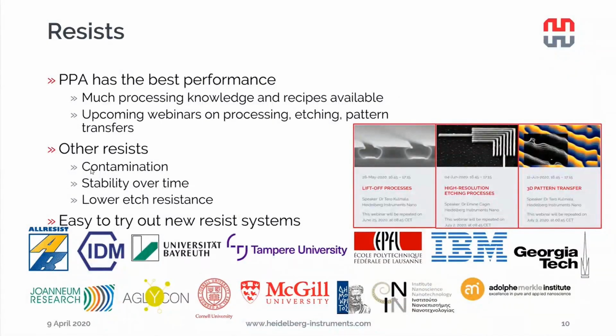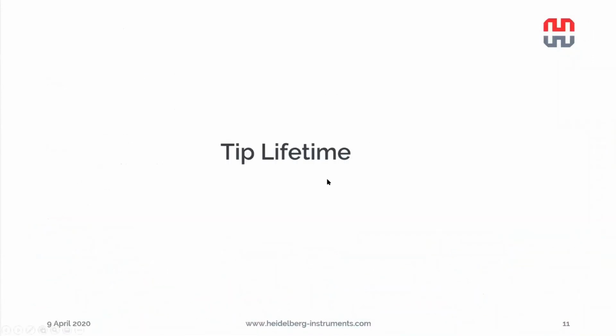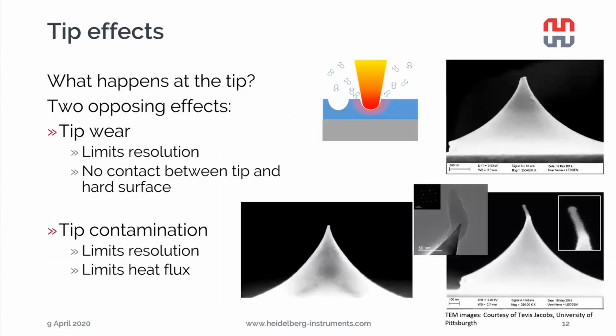Now I talked a lot about this contamination, and in the second part of this webinar, we will have a closer look at the tip lifetime, this tip contamination, what happens at this interface. So at the tip, we have basically two opposing effects. We have tip wear and tip contamination. The tip wear happens when we move the tip across the surface and it gets worn down.